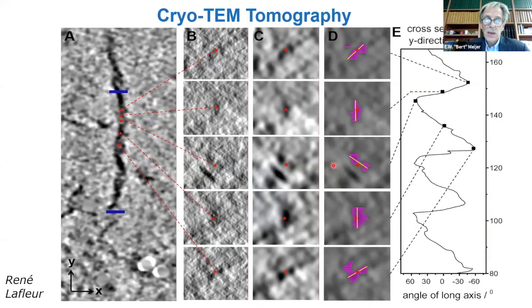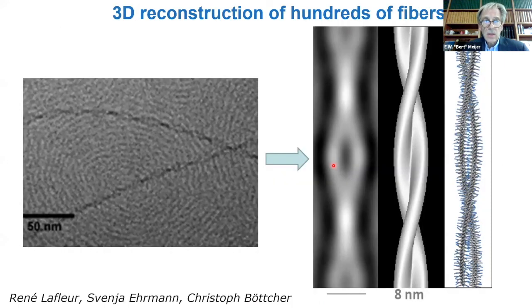We use cryo-TEM tomography to go into more detail. This is a very difficult slide to follow, but it gives the idea that it is not something that is a single chain, but it looks like there are two chains together. Then together with the people in Berlin, we did a 3D reconstruction of hundreds of these fibers. And if you do so, there's no other conclusion than that what you get is a double helix based on individual molecules that really go as a 2D structure. In the beginning, we really had trouble to understand why that is, but I think it's a hydrophilic balance that makes it into a bilayer.